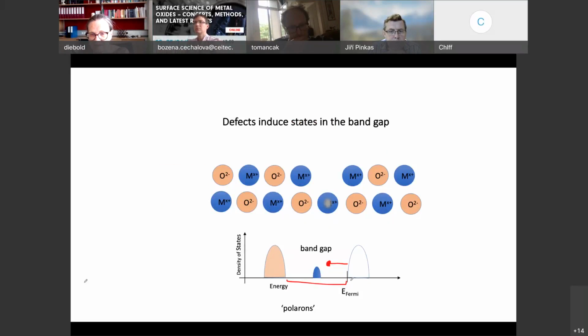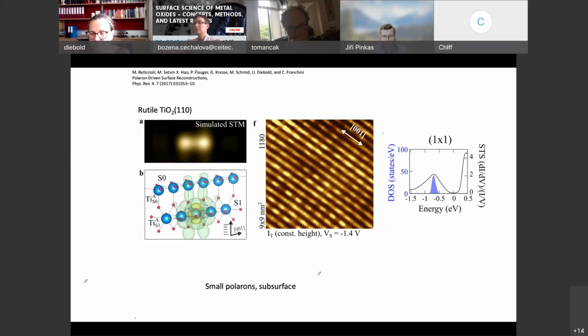Valence band, filled states, Fermi level, conduction band, empty states, band gap. The blue is the calculated density of states. You can see there's a very nice sharp feature. Those are these extra electrons that are left behind and put into the sample because you remove oxygen. Here is the reference level, the Fermi level at 0. This is the conduction band minimum. These are experimental spectra, taken by parking the tip on top of the sample and ramping the bias voltage, positive and negative voltages. One can measure this gap state, and it agrees quite well with these DFT calculations.